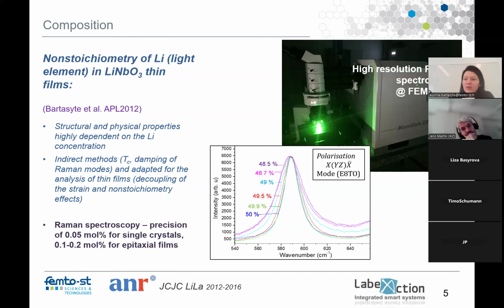It's very precise. You can do a mapping of the concentration. Here we have an example in lithium niobate of how the width of the Raman modes changes, which are sensitive to the number of defects. So we can get the composition very precisely if we have a calibration. In single crystals, we can measure the lithium composition with a precision of 0.05 mol percent.